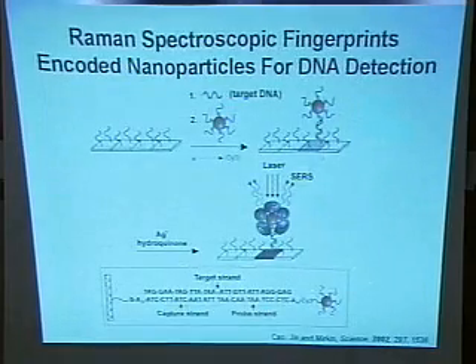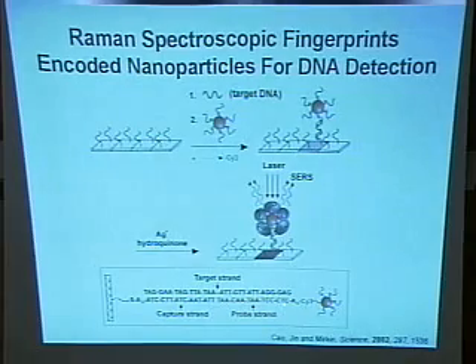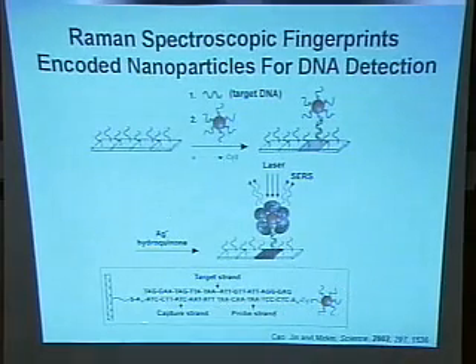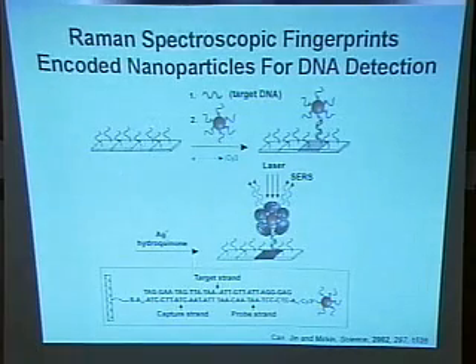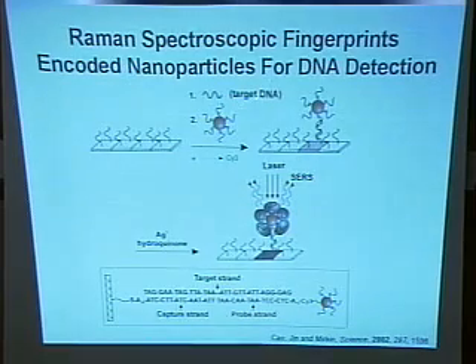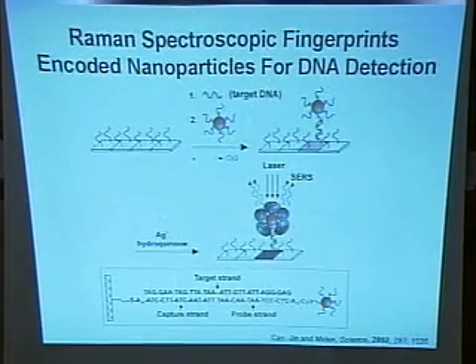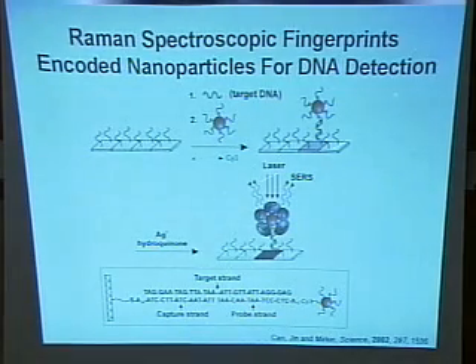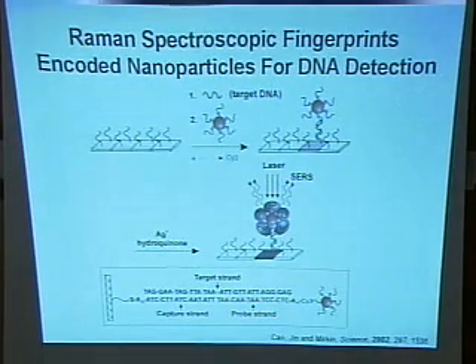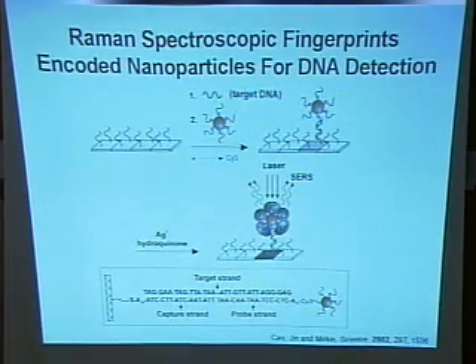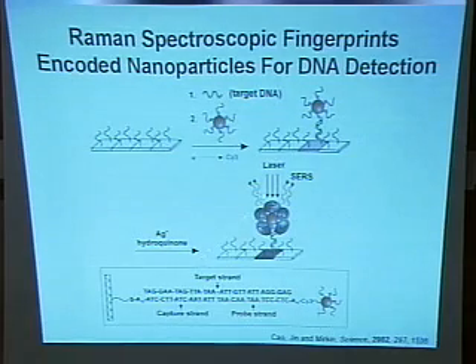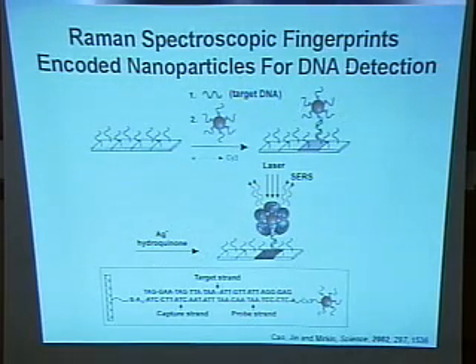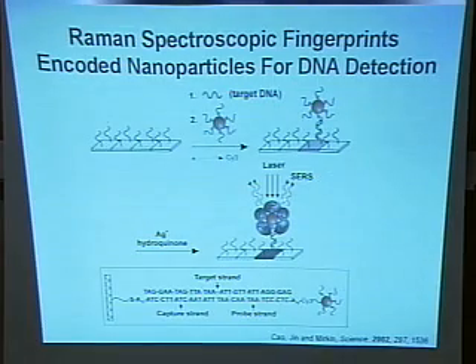So first, I functionalize a Raman dye labeled oligo probe on the gold particles. And this capture was attached on the surface of the chip with a desired target. So the particles will attach on the surface of the chip. In this case, usually we detect only very low target concentrations. So this means only a few gold particles on the chip surface, which is hard to detect. However, if you do silver staining to grow silver particles around these gold particles, you will find the chip area with gold particles turns black and gives you really strong surface-enhanced Raman signal.